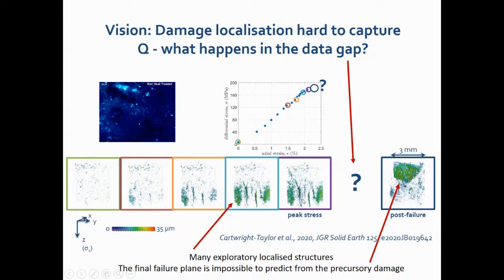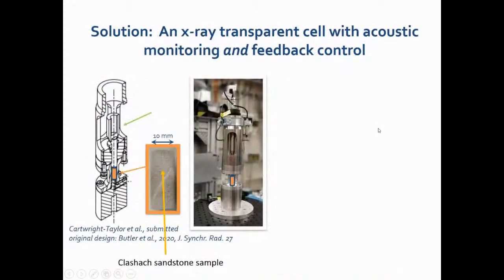We just didn't see how it went from all these little tensile features here aligned with the sample axis. How did it go from here to here? So this is what we've been able to do with the servo control in the more recent tests. And this has the sample in here and transducers top and bottom. So we can listen to the sound. And then there's a sample going in there.